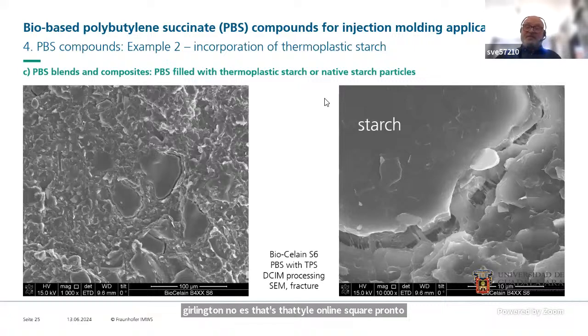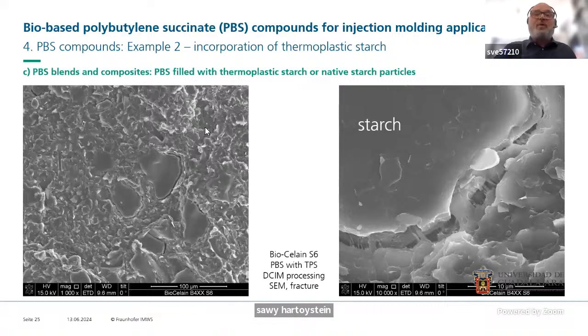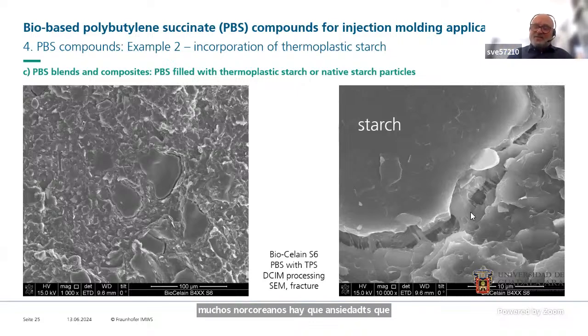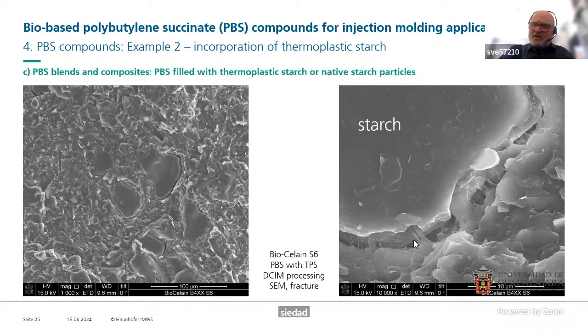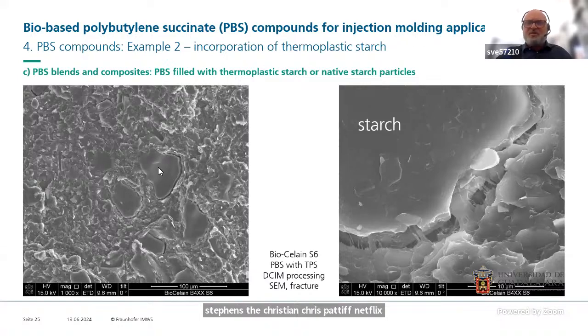Good. The other thing, just to show you another example, you can incorporate thermoplastic starches. You have the huge particles over here, which is not quite nice. That is not helping to improve the toughness, but you can see that we have a good coupling between the matrix and the starch particles, which gives us the chance to increase the stiffness, the chance to increase maybe even the strength if we have a good coupling over here, but definitely this is something that helps us to tune the degradation behavior. The material over here is degrading quite fast. We have a deterioration also of the PBS matrix, higher surfaces, and so we can increase the biodegradability by incorporating the starch into the product.